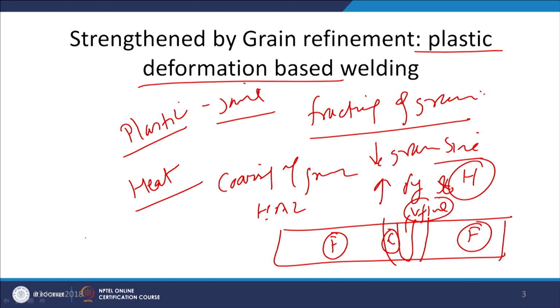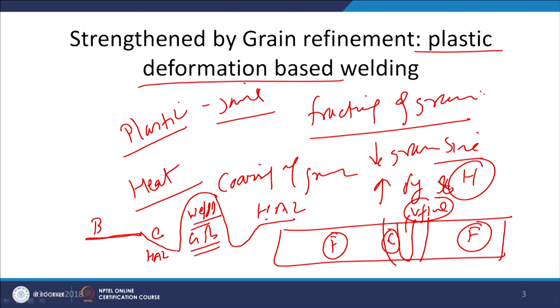So, we may find a situation where the base metal is retaining its hardness, loss of hardness is taking place in the heat affected zone due to the coarsening, and then again higher strength is being realized due to the fracturing and refinement of the grain in the weld zone. So, we may find a trend of variation in hardness of this kind. This is the weld zone having the higher hardness primarily due to the grain refinement. So, as per the change of the welding process, or as per the approach of the welding process, there can be significant variation in the yield strength and the hardness because of the changing grain sizes in case of the grain refined metal system.